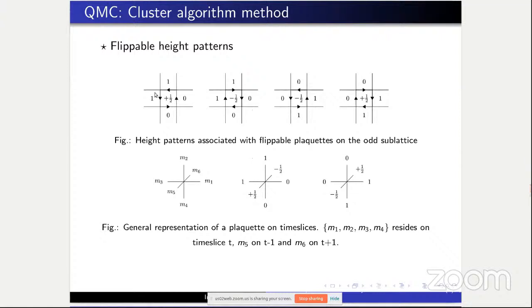Now this is the height patterns associated with flippable plaquettes on the odd sublattice. Note that there are particular patterns associated with these flippable plaquettes, 1100 or 0011. So if we change the value of plus half to minus half, we basically flip a plaquette.